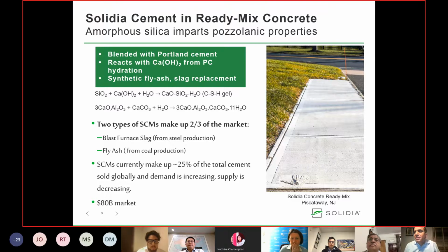In addition to this, there is a secondary reaction taking place. The calcium carbonate will react with the calcium aluminate phases, and it's going to form some monocarbonate phases. And we wanted to see if there was an opportunity in the SCM market, and two-thirds of the SCM market is composed of blast furnace slag and fly ash. SCMs currently make up 25% of the total cement sold globally.